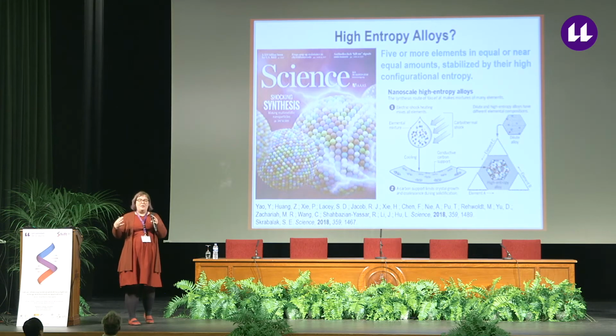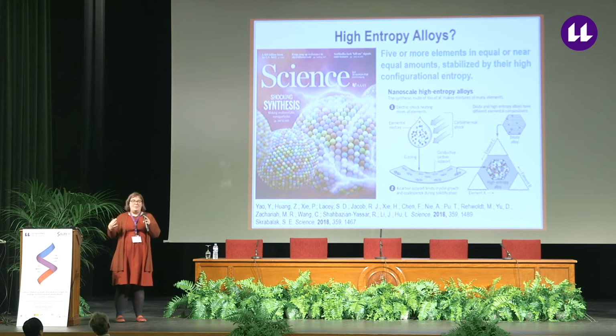And the way in which they were able to achieve this synthetically was through a carbothermal shock method. And the key features were starting with all the precursors mixed, doing rapid reduction and quenching of the reaction so that they could obtain a crystalline phase. And it was all done on a carbon support. And part of the motivation for these types of compositions is that they have the potential to break a lot of scaling laws in catalysis. But when we were reading this paper, I was amazed at the ability to make high entropy phases in nanoparticle form, but I thought this carbothermal method seems very exotic, and it would be wonderful if we could make something like this colloidally. And so my student tried.